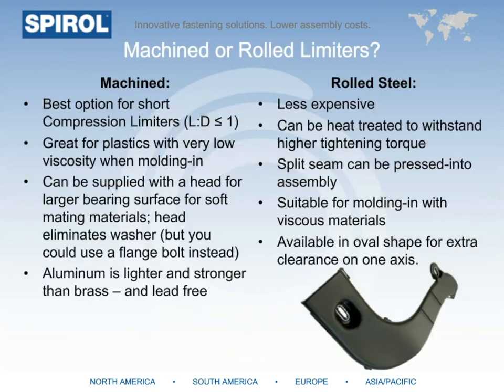And in terms of how to choose between machined or rolled compression limiters, the reality is that when it makes sense, rolled steel is definitely the most economical option. However, for short compression limiters, particularly when the length to diameter ratio is less than 1, it makes most sense to use a machined limiter because it's difficult to roll a limiter that short and keep the end square. Also, machine limiters are preferred in mold-in situations where the plastics have a very low viscosity since there are no seams for the plastic to seep into.